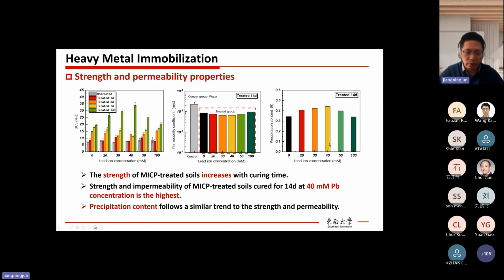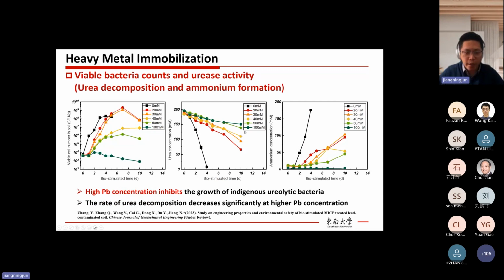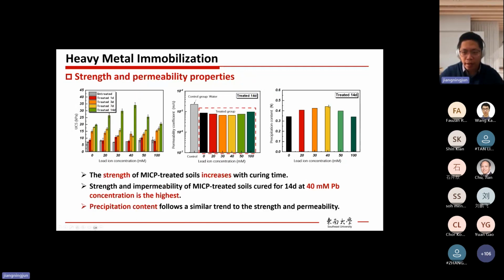So this is because we assume that while 40 millimole contaminant could retard the growth of bacteria, the urea decomposition keeps happening. So this reaction keeps happening, MICP keeps happening. So after 14 days, for the 40 case, although we didn't measure it, we can assume still a lot of urea has been decomposed. So the MICP reaction still happens a lot in this case. And because here we have more lead, right? Both lead and calcium can react with carbonate from the urea decomposition to form the precipitation. So that's why we have more precipitation at 40.